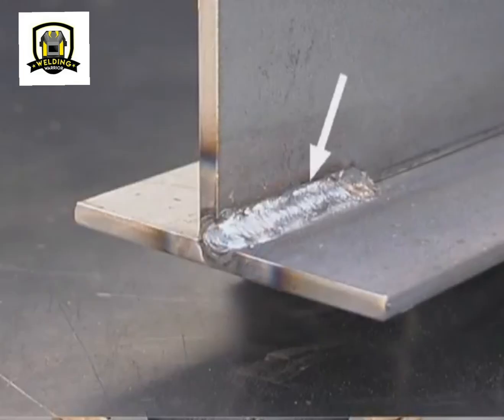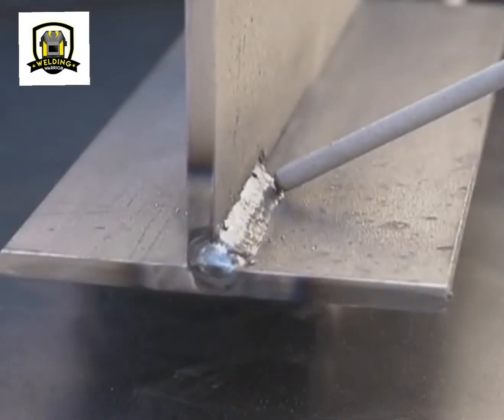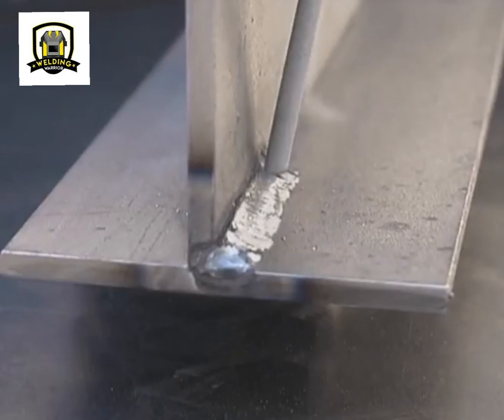On a T-joint, the top side of the weld is going to require more heat, so angle the rod into the corner to push the puddle up. If the rod is not angled enough to allow that molten pool to flow out to the top, you may leave undercut. With 60-10 or 60-11, always bring the arc back to the leading edge to fuse the corner. Angle the rod to push the puddle up. Watch the top side to avoid undercutting.